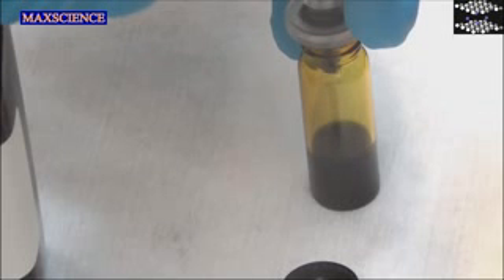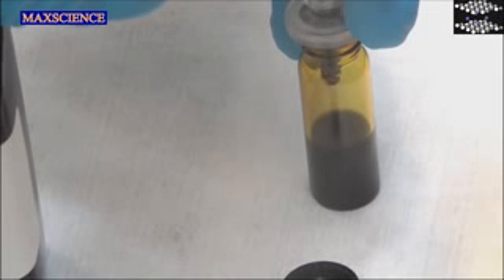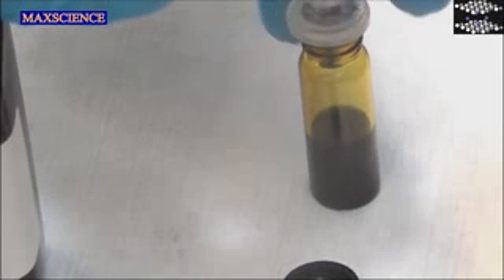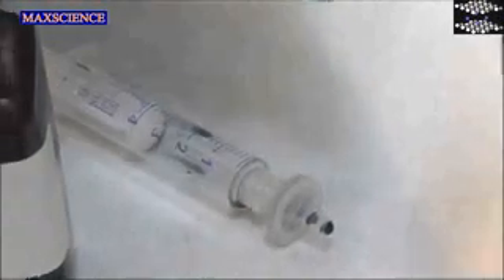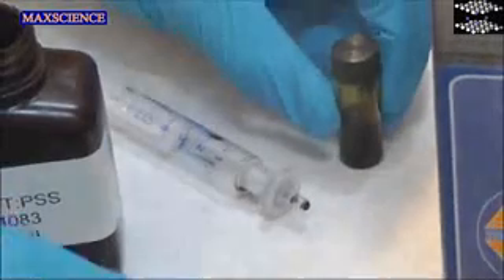After use, the PEDOT:PSS solution should be returned to the fridge for storage. The filtered PEDOT:PSS solution is then allowed to warm to room temperature, ready for deposition on the ITO patterned substrates.